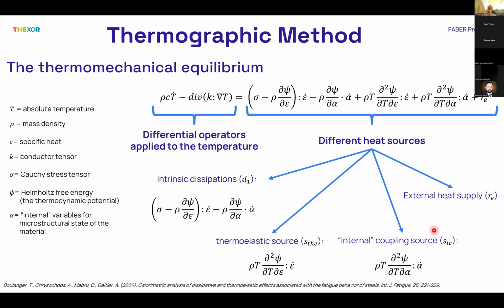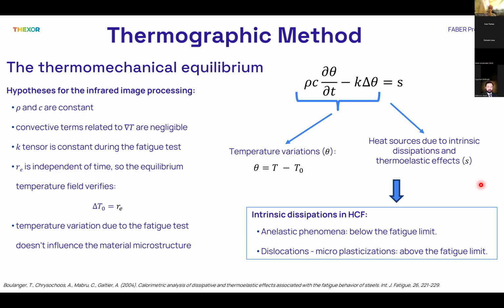And the last contribution refers to possible external heating sources. The thermomechanical equilibrium can be simplified to consider infrared image processing, with hypotheses including constant density and specific heat, negligible convective terms, and a constant conductive tensor during the fatigue test, with external heating sources considered independent of time.